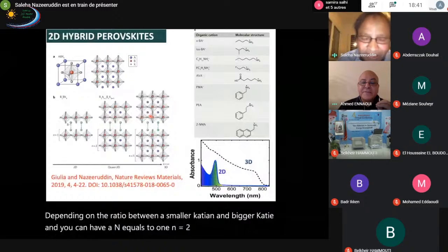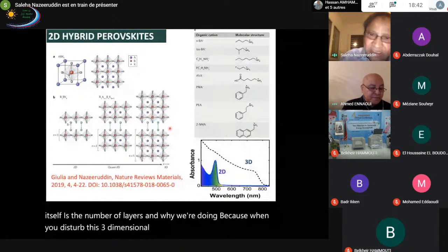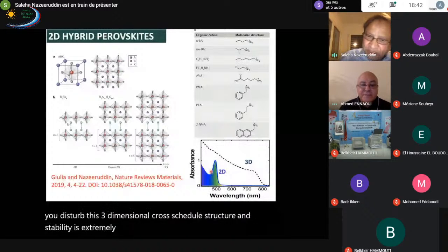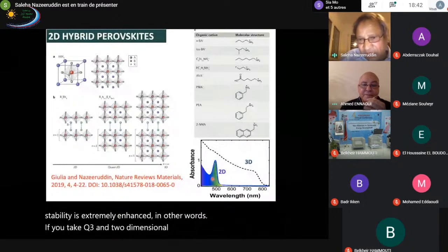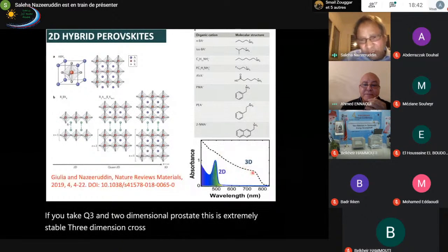And why are we doing this? Because when you disturb this three-dimensional perovskite structure, the stability is extremely enhanced. In other words, pure two-dimensional perovskite is extremely stable, while three-dimensional perovskite is much less stable. So by combining these two aspects, we want to enhance the stability. That's what we want to do. So the next slide is a characterization aspect.